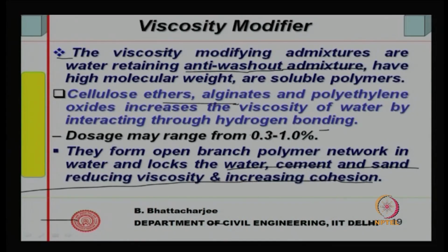Dosage may range from 0.3 to 1%, all right. So, these are viscosity modifiers used in underwater concreting, and nowadays in some of the self compacting concrete.